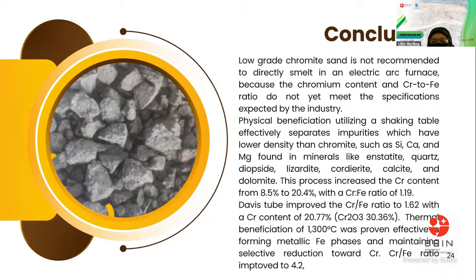This process increased the chromium content from 8.5% to 20.4% with a chromium to iron ratio of 1.19. And then the Davis tube magnetic separation improve the chromium to iron ratio to 1.62 with chromium content of 20.7%. And the last is thermal beneficiation has improved the ratio of chromium to iron to 4.2.